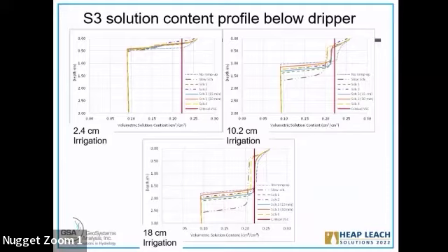And with 4 inches of solution, you can see here, the collapse at shallow is still there. And all other scenarios went higher, but they're very close to the critical one. They did not exceed. But when you apply about 7 inches of solution, only the scheme 4 and then the slow scheme survived.